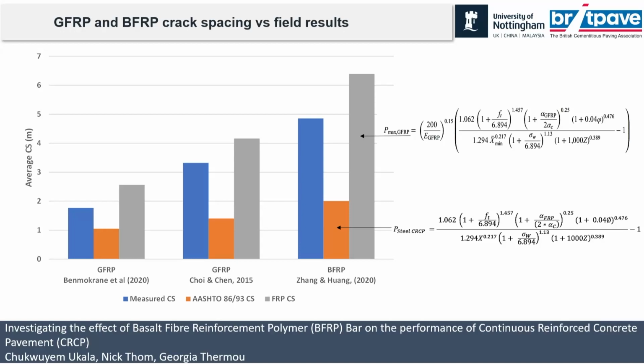But what we did was we calculated what we expected to be the crack spacing, given the values in the literature, and we compared this here, using the steel, and we did the same using the Benmokrane modified FRP equation. And what we see here is that this is that of the steel model, and this is what was measured by the research. And what it's telling us is that it's about halfway of the basalt, which generally is what we've come to see from our sensitivity analysis to an extent. The same thing followed using the glass fiber. However, when we use the model shown here, we saw that it actually overestimated the crack spacing which we had in the literature, but the difference was not as much.